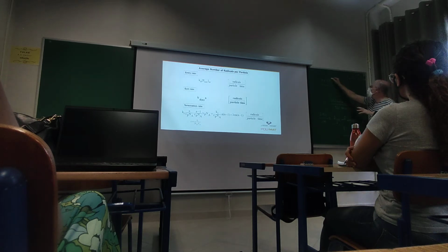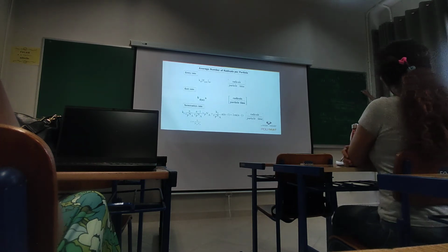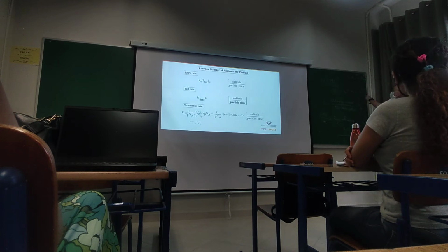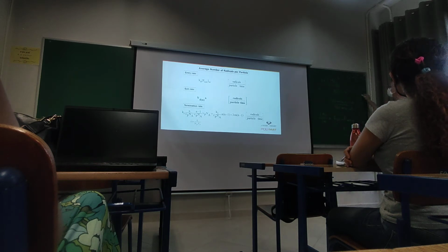Even if the concentration of radicals is of this order in a homogeneous system, in a bulk or solution polymerization, if you multiply this by Avogadro's number, the number of radicals is of the order of 10 to the 16. However, in an emulsion polymerization particle, you have 1, 2, 3, not 10 to the 16.